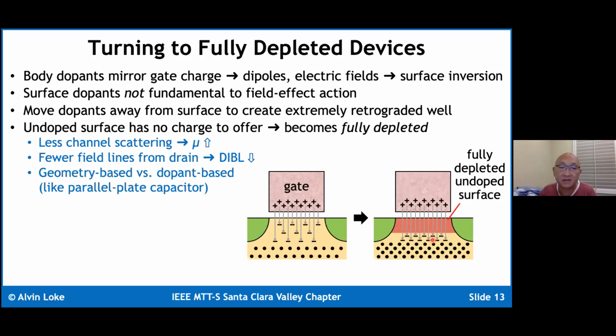And there are some benefits in doing this. When you have the so-called fully depleted undoped surface, because you have no dopants right at the surface, you have a lot of goodness. One goodness is that because you have very minimal dopants along the surface, you have a lot less channel scattering, which means that your mobility gets better, okay? Furthermore, because you don't have field lines terminating inside here because you have no charge, the drain charge will terminate downwards deep into the body, which means that the drain charge has very little control over this depletion region you're trying to control with the gate, which means that drain-induced barrier lowering actually gets lower, which is a thing of goodness.